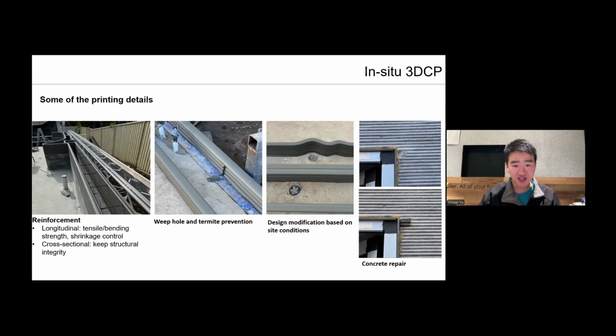And here are some of the details we made on site. Firstly, just like traditional concrete, we always need reinforcement. For printed structures, we typically use longitudinal reinforcement along the filament path, as well as cross-sectional reinforcement to tie the wall together and ensure structural integrity. Next, simple construction details like weep holes and termite prevention are actually much easier with concrete printing. Because the concrete is still in a semi-solid state, we can simply cut it by hand when it's still fresh, so no drilling or complicated formwork is needed.